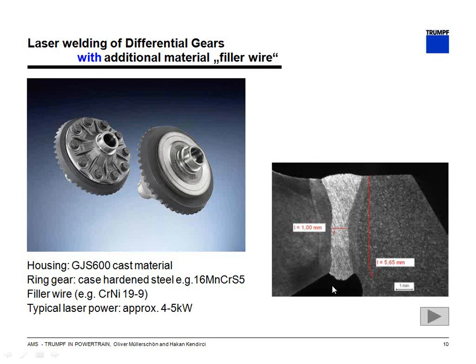Here you can see a typical cross section on the right side. This welding is made with a solid state laser with a filler wire feeder system. Typical materials you can see here on the left side, also an example for wire material. Typical laser power for this application is about 4 to 5 kilowatts.